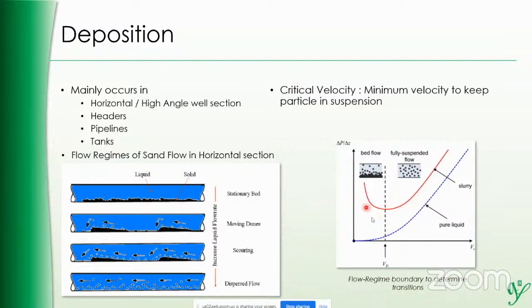I don't want to go into those details, but this is just to show that if you look at the velocity and the pressure drop, going from the right to left here is the same as going from bottom to top here. So as your velocity decreases, if there was no sand, only pure liquid, you see your pressure drop decreases until zero, even to a certain point. But on such a system where there's a bed flow and fully suspended flow, after a certain while, because of the nature of this stationary bed and moving dunes, you will see a little increase in the pressure drop.